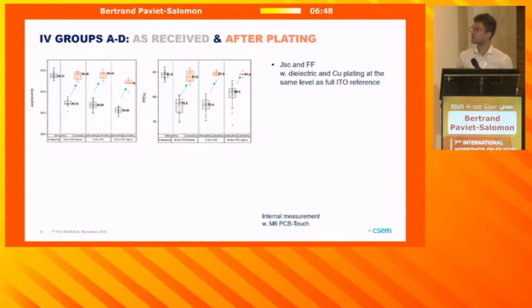Similarly, for the fill factor, as received, the grid resistance is too high to perform well, but after plating, we again raise the fill factor to a value similar to the full ITO, full silver baseline.